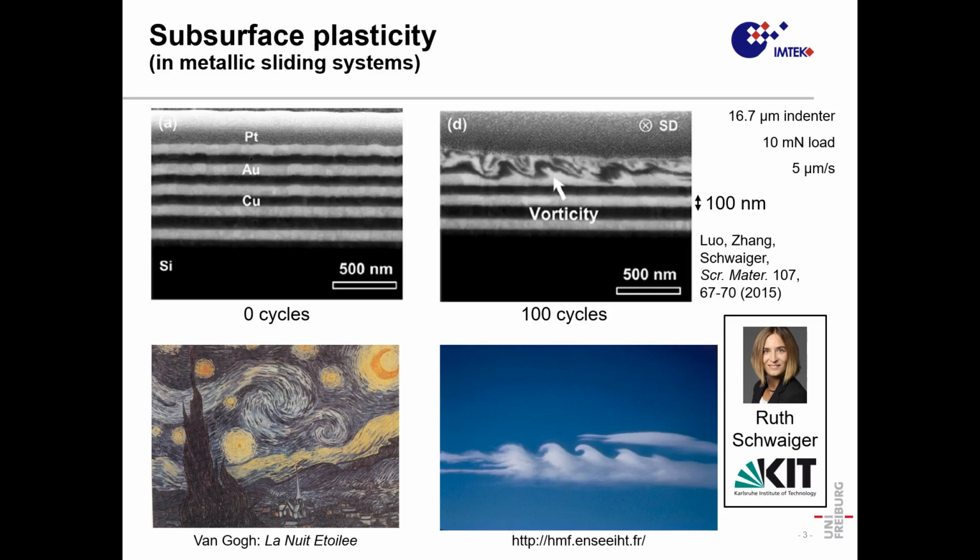One problem understanding what's happening is, of course, that you need a way to measure the strains introduced into the surface. And that is difficult in general because essentially you need a tracer that allows you to track the deformation of the material. And a very neat class of systems that actually have sort of a tracer built in are metallic multi-layer systems. And what you see on this slide is an example of a copper-gold system that has nice contrast in electron microscopy. So you can nicely identify these individual copper and gold layers that have been sputter deposited on top of each other.